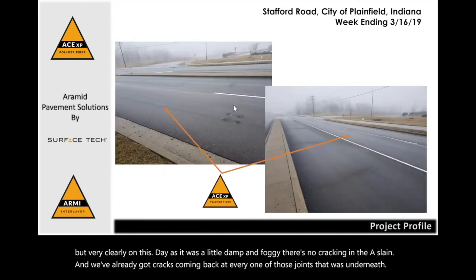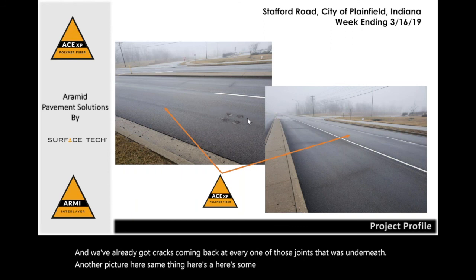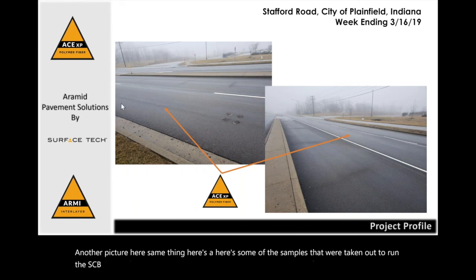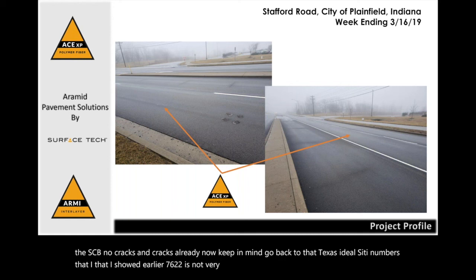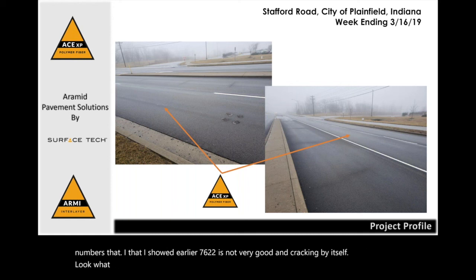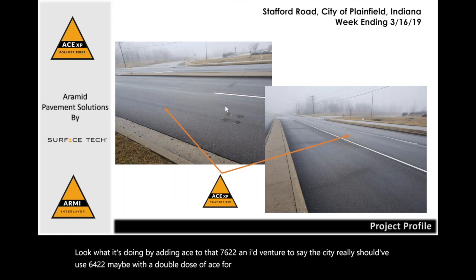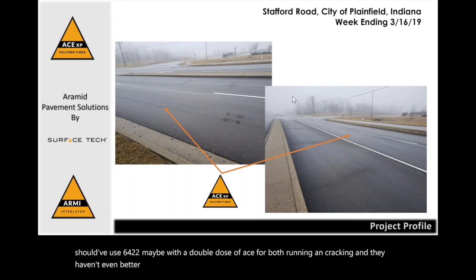Another picture here, same thing. Here's some of the samples that were taken out to run the SCB. No cracks, and cracks already. Now, keep in mind, go back to that Texas ideal CT numbers that I showed earlier. 7622 is not very good in cracking by itself. Look what it's doing by adding ACE to that 7622. And I'd venture to say the city really should have used 6422, maybe with a double dose of ACE for both rutting and cracking, and they'd have an even better product today. But that's where we're at.